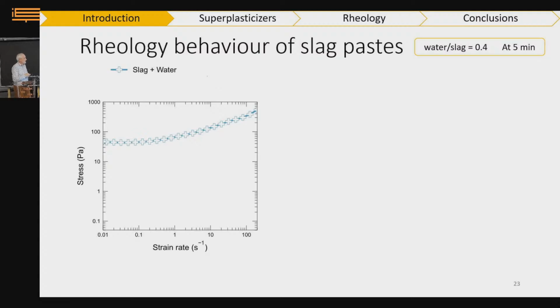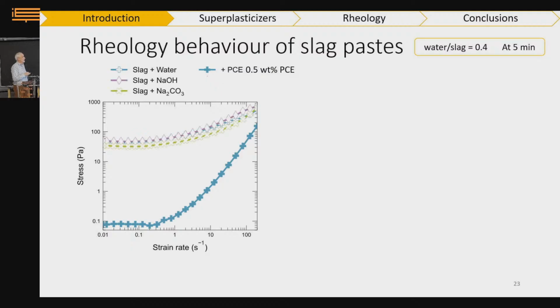Again, the shear stress that you observe on a suspension of slag in water. With superplasticizer, you depress the yield stress, and if you add the activators, here sodium hydroxide or sodium carbonate, you see that the efficiency of the superplasticizer is lost. You recover the initial curve as if you had put no superplasticizers in it, right? So clearly they are not compatible, or at least their effects are not compatible. You cannot use the superplasticizer you use in ordinary Portland cement in activated materials, in presence of activators.